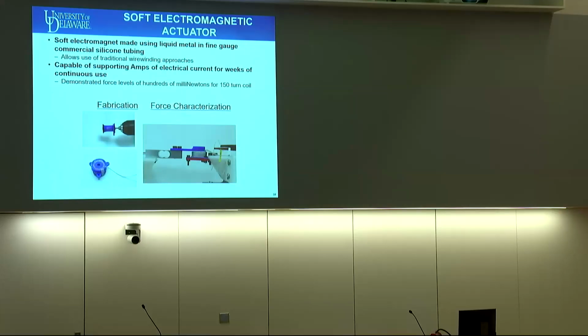So we decided, can we use a fully soft electromagnetic actuator to drive something like a robo squid or a squid-like motion? And using the silicone tubing approach that Dr. Dickey had developed, we used this fine gauge to make a very soft electromagnet using just traditional wire winding approaches. My student just took a drill and wrapped the silicone tubing and was able to make up to about a 150 turn liquid metal coil using this approach. And we characterized the force levels you can generate, and we're up in the hundreds of millinewtons for this 150 turn coil. So again, an impressive level of performance for a fully soft actuator.